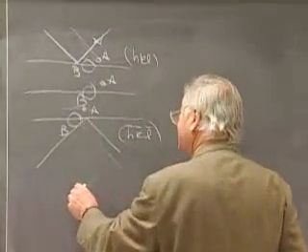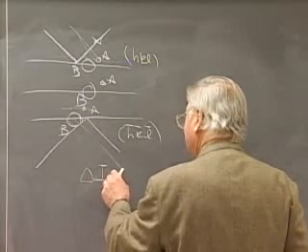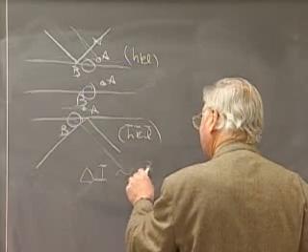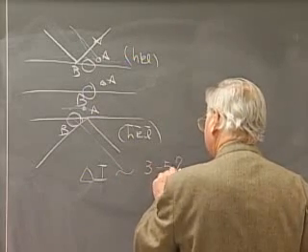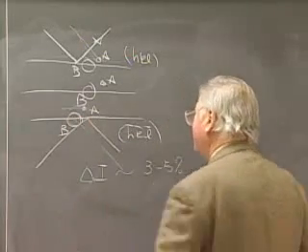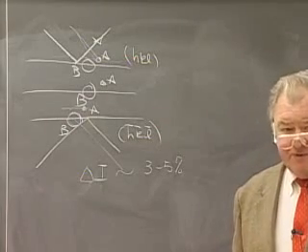atom the X-ray beam encounters first, and the difference in intensity is on the order of 3 to 5%, although by picking a radiation appropriately for the particular chemical species in the crystal, you can increase this perhaps to 10 or 12%.